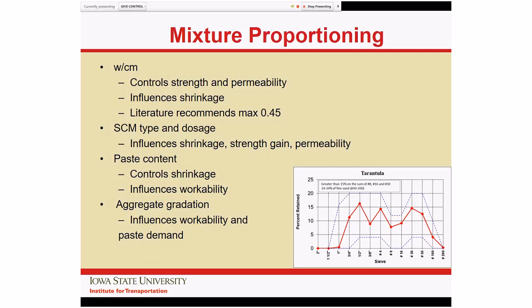Another one that people don't think about an awful lot, but I'm trying to change that, is to look at how much paste there is. The mixture of cement, cementitious material, and water. The more there is of that in the system, the higher the shrinkage is going to be, because it is the paste that shrinks when it dries. And so we want to try and limit that number. And the way we can do that is by paying close attention to the aggregate gradation. It strongly affects workability as well. And so we're playing a juggling game of getting enough workability for the contractor to be able to place the concrete, at the same time not putting in too much paste, because that is generally negative. Increases cost, increases heat of hydration, increases shrinkage.